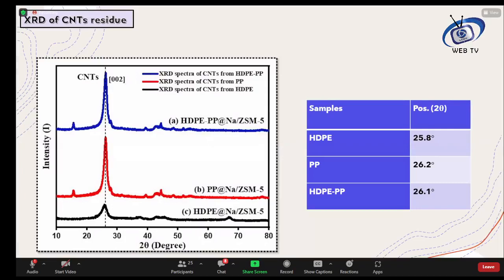Thereafter, for the solid residue, which we assume is carbon nanotubes, we performed XRD analysis, and we observed peaks at 2 theta of 25.8 degrees, 26.2 degrees and 26.1 degrees. The corresponding plane was 002, which shows that these were multi-wall carbon nanotubes. Some other peaks in the XRD analysis were also observed, which may be due to amorphous carbon, the catalyst, or the heat susceptor itself.